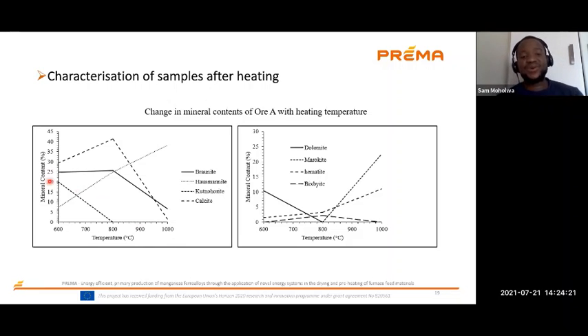Here we have the mineralogical changes in OA that is being heated. We can see that haussmannite is increasing when you are moving from 600 to 800, and it further increases when you go to 1,000. We have kutnoharite here. It's dropping when you are moving from 600 to 800. In this case, kutnoharite drops to 0, because if you remember, the literature revealed that kutnoharite decomposes at 700 degrees Celsius. So it makes sense that here we literally have none of kutnoharite at temperatures above 800.